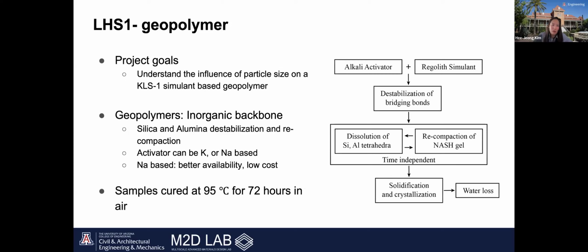In the first study, we examined how particle size affects the compressive strength of the regolith simulant-based one-part geopolymer. As some background, one-part geopolymer is formed by reacting a precursor powder, rich in amorphous silica and alumina, with a highly alkaline solution. The alkaline activator breaks the bond between silica and alumina tetrahedra, dissolving the powder into a paste. And this paste can be cast or extruded to form a solid part.